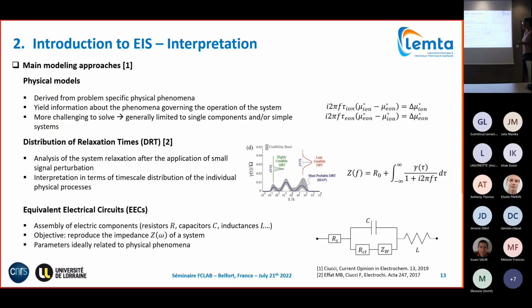Another technique is the distribution of relaxation times, meaning you apply a small perturbation to your system and you measure the relaxation after the perturbation, and separate the relaxation according to different relaxation times. So you can interpret the relaxation in terms of the timescale distribution of the individual processes. For example, mass transfer processes and diffusion phenomena are very slow, so they will occur at high relaxation times, and charge transfer phenomena are very fast, so they will occur at very low relaxation times.